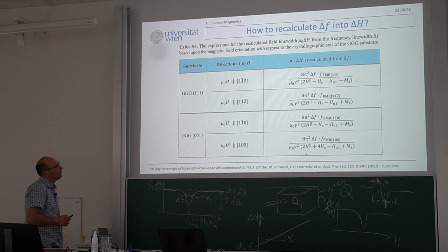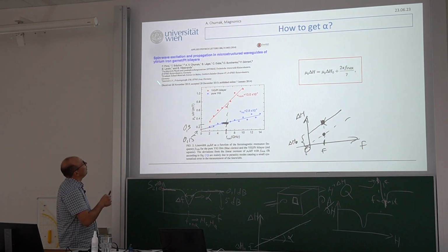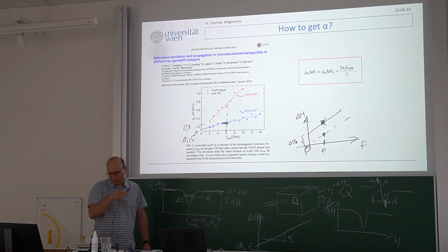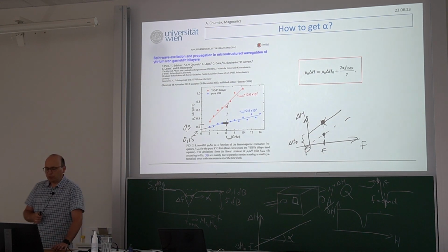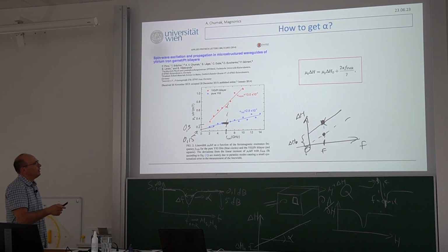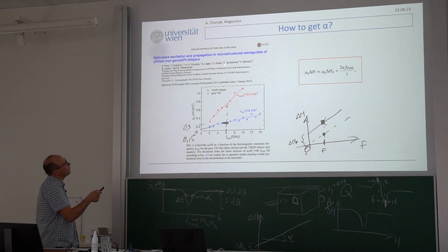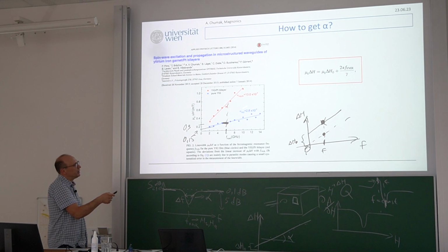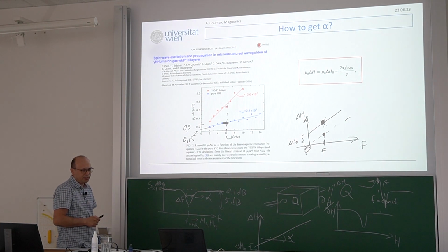And here then is just an example from one of our papers, with some handwriting on a tablet from a long time ago. Notice that's how it looks. For example, you take yttrium iron garnet. It's liquid phase epitaxy grown by Carsten Dubs at Innovent in Jena, with alpha of 2.8 times 10 to the power minus 4. It's actually his first 100 nanometer thick YIG.